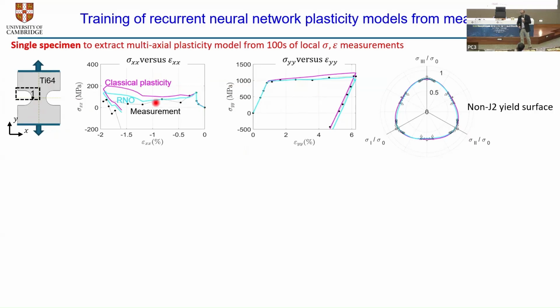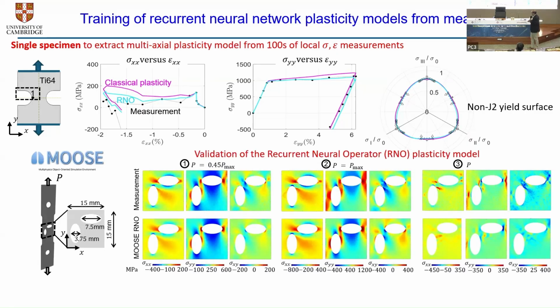What I'm showing you here is the measurement, which is these black things, and two different models. Classical plasticity models, the best possible classical plasticity model that we could come up with, actually doesn't do that great a job in predicting the strain hardening behavior. And that is the yield surface that we are showing you here. This titanium doesn't behave like a typical, what we call in plasticity theory, a von Mises material. We've also developed what is called a recurrent neural operator model, which is a neural network model. This is the comparison between the experimental data on the top row and the neural operator prediction of what that curve looks like.